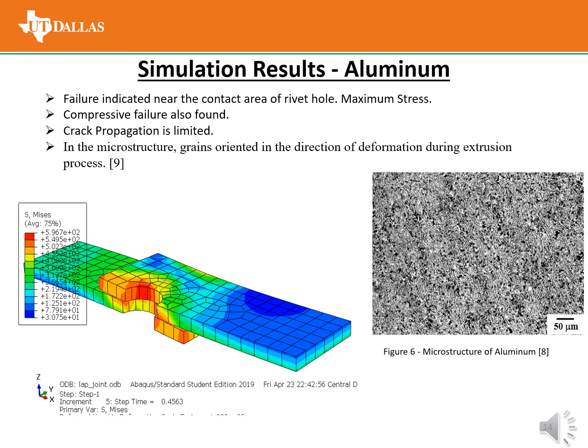Now we move on to the simulation results for the first material, that is aluminium. Here in the figure we can see that the maximum stress or the failure is indicated near the contact area with the rivet, while a compressive failure is also found at the ends of the plate. While the crack propagation here is limited, the microstructure of the grains are oriented in the direction of deformation during the extrusion process.